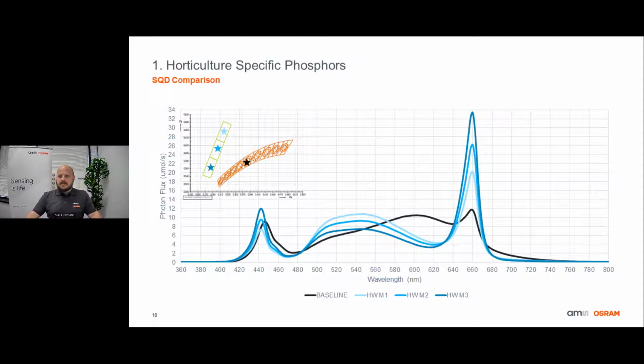The shifted phosphor of the Horti White is going to increase the green content in the lower portion of the green between 500 and 560. And blue, for the most part, is relatively unaffected, though the peaks are moving around a little bit. Any variation you do see here in the data of the actual wavelength of the blue peak is just because of the data that's been used. The target peak wavelength is the same for our Horti White as it is for all of our general white products.